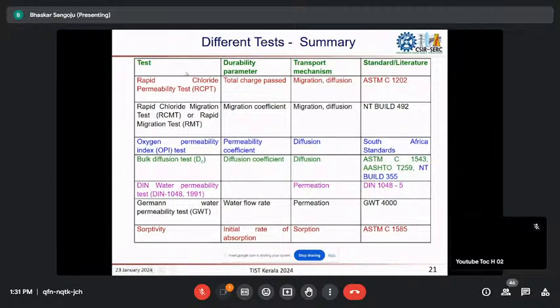So, for example, in the rapid chloride permeability test, the total charge passed is being evaluated, and the main transport mechanism is migration. Because, as I said, in most of the accelerated tests the dominating mechanism is migration, and it is reported and followed using ASTM C1202. Like that, rapid chloride migration: the migration coefficient is the durability parameter, migration or diffusion is the transport mechanism, and NT Build 492 is the standard available in the literature, that is the code.